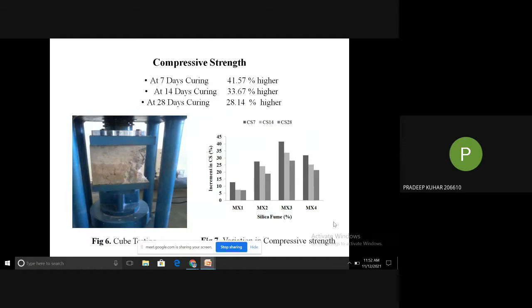Thereafter, I tested the cubes for compressive strength, and the specimens showed an improvement in compressive strength. With the addition of silica fume in the concrete, the optimum amount was figured out as 9.5% replacement of silica fume. That is, MX3 specimens showed the highest compressive strength. When we compare with the normal concrete, that is MX0 specimens, at 7 days we get 41.57% higher compressive strength, at 14 days 33.67% higher, and at 28 days 28.14% higher.